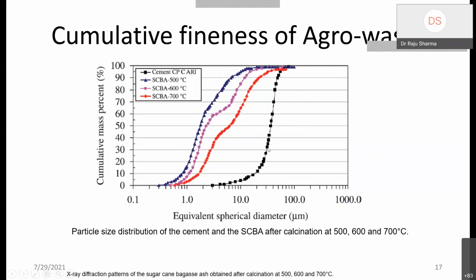Let me just show you the fineness of the different agro waste. Here I am showing the sugarcane bagasse ash, which is calcined at 500, 600, and 700 degrees Celsius. They prepared the fineness modulus and the cumulative percentage fineness, and they saw that yes, the product is very fine as compared to the cement. So one thing is very clear: it will improve the packing behavior of the concrete. The packing behavior of the concrete definitely changes when you use it as a percentage replacement in concrete.